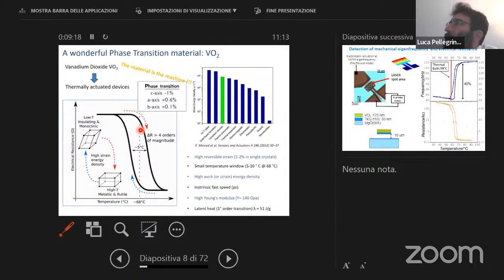So now I move to a wonderful material, which is vanadium dioxide, and we have been studying this material for a long time in collaboration with Japan, and they are making nice films with very good quality. And we are also performing experiments by fabricating MEMS and making the measurements. So I will just briefly outline some of the main properties of this material. This oxide has a resistive transition, a phase transition, above room temperature at about 70 degrees Celsius, which is quite sharp. This is made from a film and is 4 orders of magnitude. And at the same time, you have a change of the crystalline structure from monoclinic to rutile.